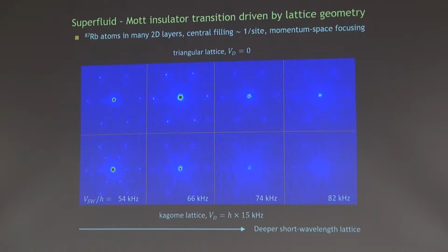And for us, deepening the lattice is equivalent to severing the connection between sites and making the on-site interaction more significant compared to the tunneling between sites. But you see already in these images, just qualitatively, that the superfluid lives longer. It is retained to stronger, deeper lattice depths. So lattices that have even less tunneling in the triangular lattice than in the Kagome lattice. So clearly, just from this picture, you can see that this structural change can drive superfluid gases into the insulating state by severing ties within the lattice.